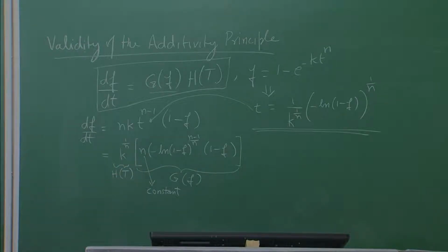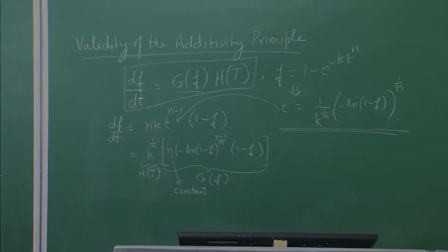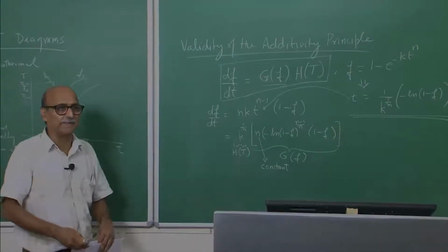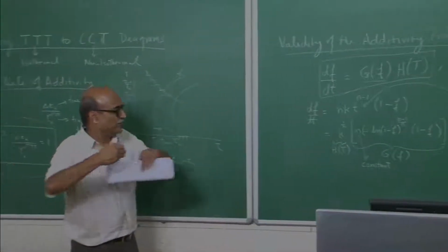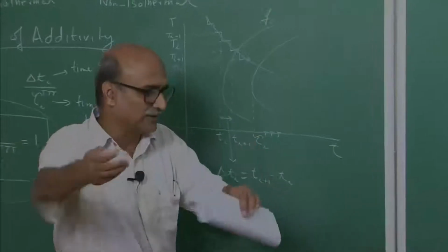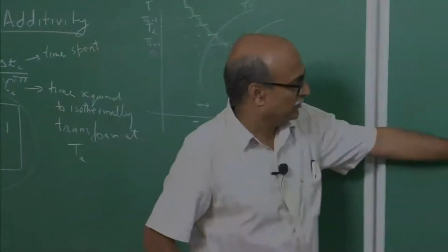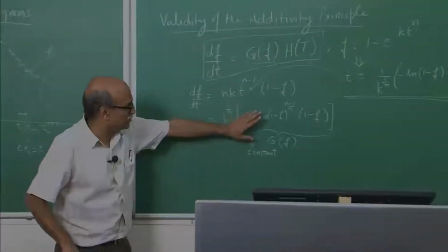You know, whether the mechanism is heterogeneous, homogeneous, whether there is site saturation or not. If you go back to the starting lectures, we had shown that if there is site saturation, you get a certain value of n. If you have constant nucleation kinetics, you get a certain value of n, while k could vary. So, we could make statements on n.